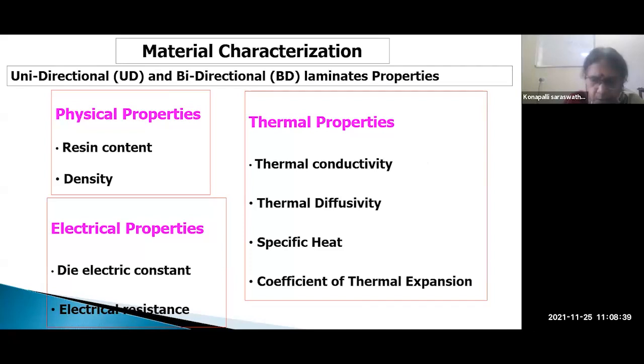As I told you, the mechanical, then physical properties, resin content and density, we measure on samples. Resin content, if we measure directly by weight, it will give the volume fraction of the composite, because generally we consider a 60% volume fraction, means fibers are 60% by volume in a composite. So we generally find out resin content and density.